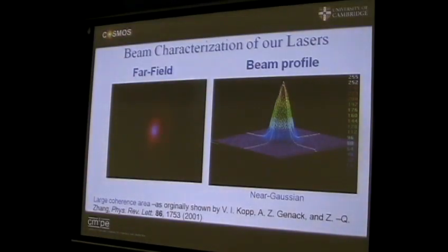What I can't tell you, that's the transverse mode. We haven't done the spectral analysis for the longitudinal mode. But given the narrow line width, I think that's where it's likely to be monomode. It's not like a conventional cavity where you can set up lots and lots of standing waves. It's a property of the dielectric properties of the helix. And if you go through all the theory, you find that these things should give you single longitudinal modes. It's an averaging effect, as well as single transverse.